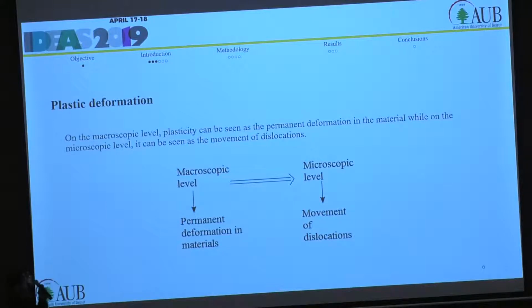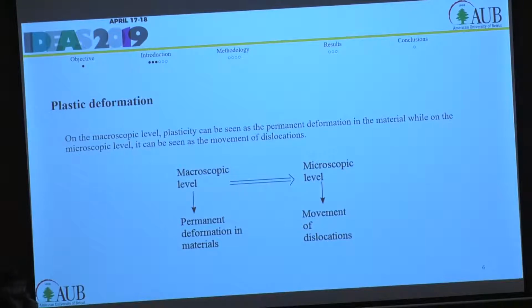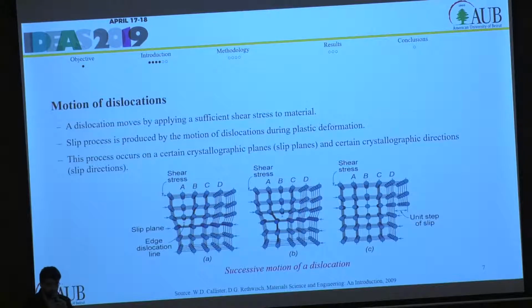So by subjecting material to a load that exceeds its yield strength, it will undergo a plastic deformation, and this plasticity could be seen as the permanent deformation on the macroscopic level. However, at the microscopic level, this can be seen as the movement of dislocations. So how do dislocations move? Actually, they move by applying a sufficient shear stress above a certain critical value.